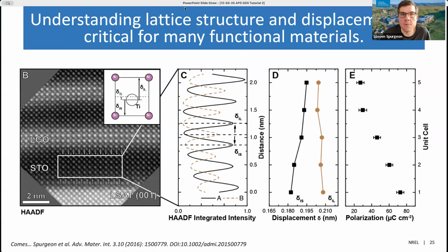In much of my past work, we have been looking at materials like ferroelectrics. These are materials that exhibit spontaneous polarization that could be switched and is persistent. In some of the earliest work that we did here in some of these superlattices, lanthanum chromite and strontium titanate, what we were looking at was high resolution imaging, in which on the left here, you're looking at a high angle annular dark field image. The bright spots in this image correspond to heavier atoms. We're seeing a periodic array of these atoms, so a crystal structure. This material is a superlattice, so it's a series of layers. Understanding how polarization and atomic displacements vary within the superlattice is critical to controlling any devices based on this.